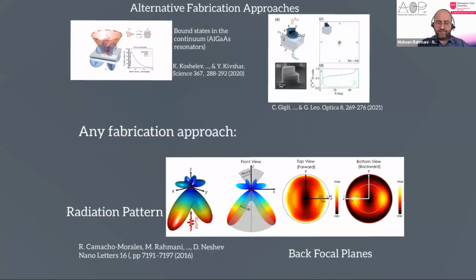And then they generate them, and they could study the forward and backward. But another main issue in these III-V semiconductors was that they have zero emission at normal incidence because of the very complex second order susceptibility. As you see over here is the nonlinear emission. So it is the pump, the fundamental coming here, and you see in the normal we don't have anything. If you see from the front view, in the normal we have almost zero.